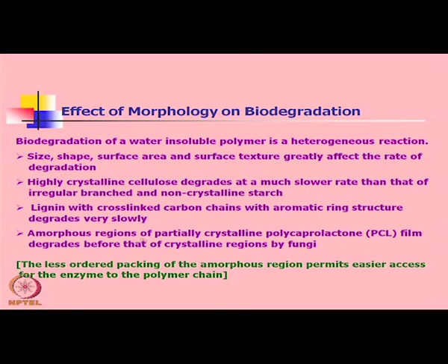Amorphous regions of partially crystalline polymers, like a partially crystalline polycaprolactone film, degrade before the crystalline regions by fungi. So, it has been established that if a polymer is amorphous, it will be degraded faster.